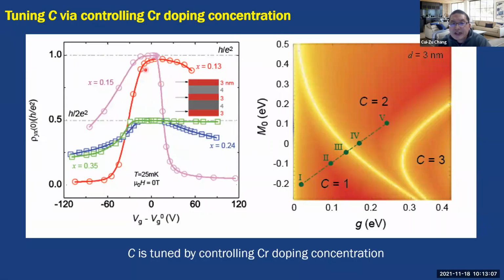And this Chern number tuning is further demonstrated by the gate dependence of the zero magnetic field Hall resistance. We can see that with the lower doping level it is quantized at h over e squared, and at higher doping level quantized at h over 2e squared. Our experimental result is well interpreted by the theoretical calculation by my colleague, Professor Chang in our department.